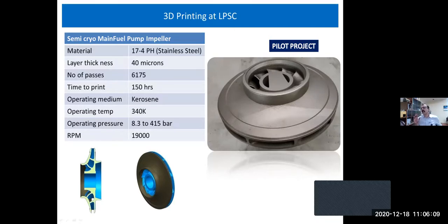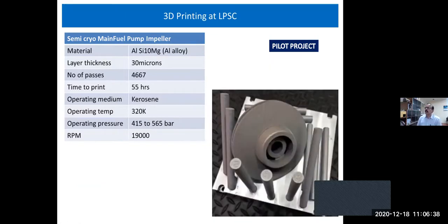Earlier, these used to be cast or made as two different pieces. Then you machine out all the vanes. On the left, you see very complicated vane profiles. Machine it out and weld. So it takes a long time. We have 3D printed it, 150 hours, continuous working. So 150 divided by 24, how much is it? Roughly 6 days. That's an amazing achievement.